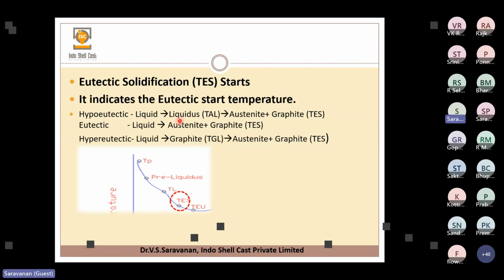So liquidus, liquid, from that the austenite precipitates, and then the graphite comes at TES. So that is hypoeutectic. And then eutectic, at that particular point both austenite and graphite simultaneously precipitate. So that is the eutectic point. Hypereutectic means first the graphite will start precipitating and then austenite will start precipitating. So these are all the things, and this particular thing happens at TES.